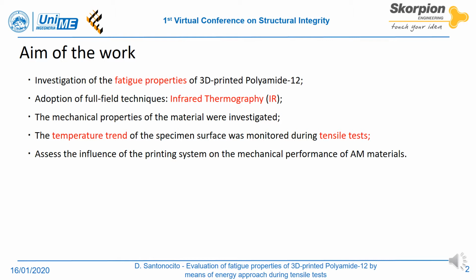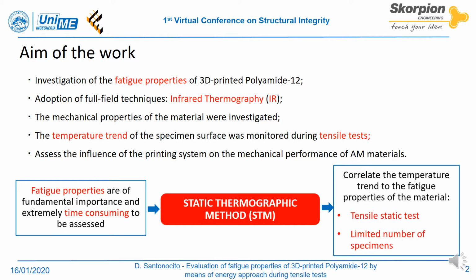infrared thermography. The mechanical properties of the material were evaluated and the temperature trend of the specimen's surface was monitored during tensile tests. The fatigue properties are of fundamental importance for a proper design of mechanical components, but they are extremely time-consuming to be assessed. In this work, for the first time, the static thermographic method was applied to 3D-printed material in order to correlate the temperature trend to the fatigue properties of the material during tensile static tests, adopting a very limited number of specimens.